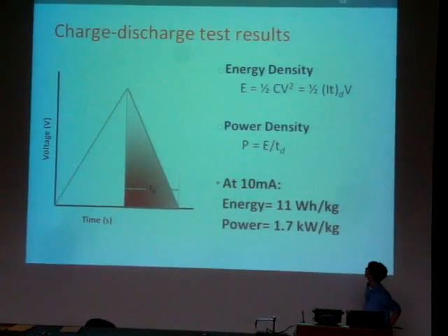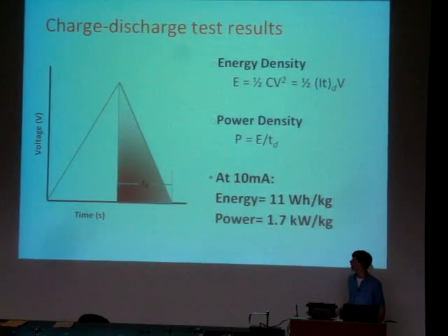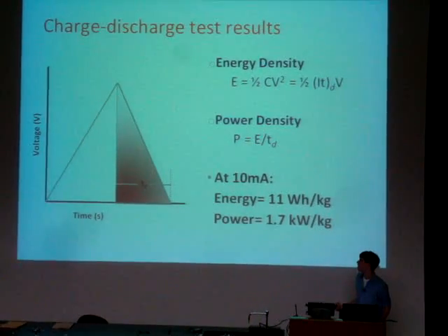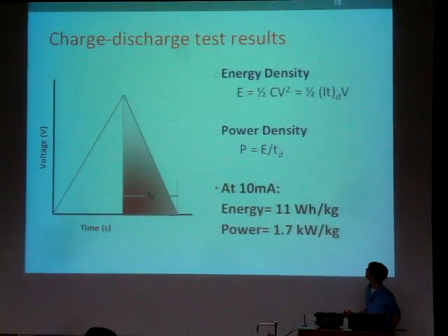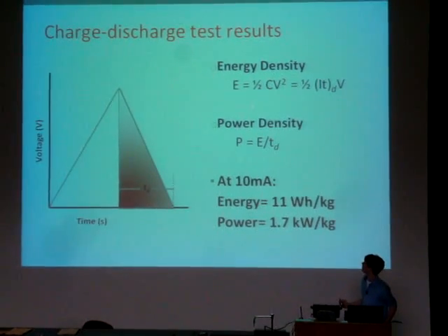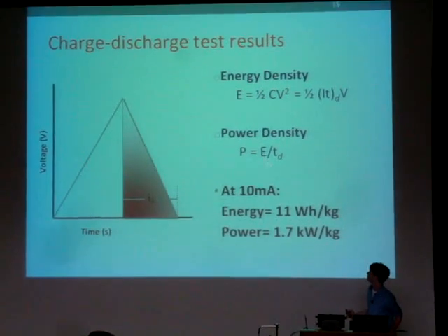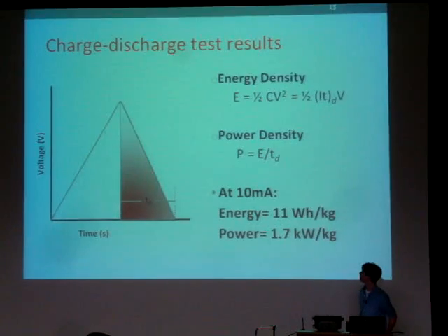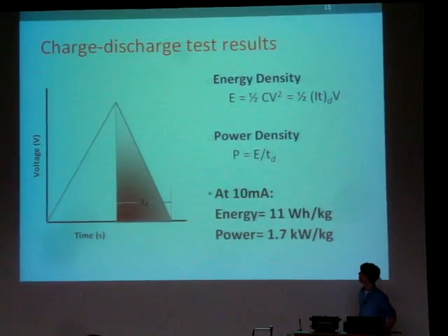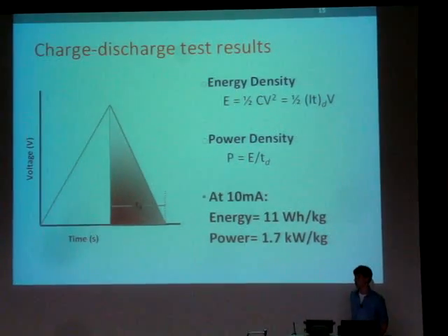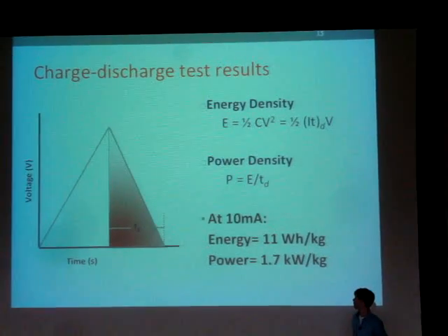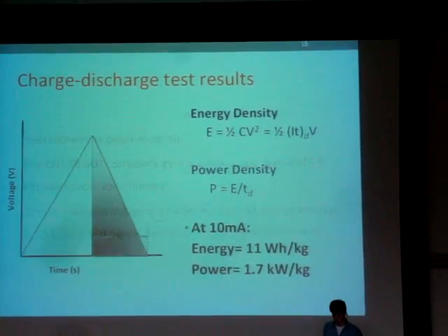Over here are the charge-discharge results. The charge-discharge test helped us find the power and energy density. We ended up determining the discharge time. And after that, we found the energy density, and then after that, it's simple to find the power one. And at 10 milliamps, we ended up getting the desirable energy density of 11 watt-hours per kilogram, and a power density of 1.7 kilowatts per kilogram.